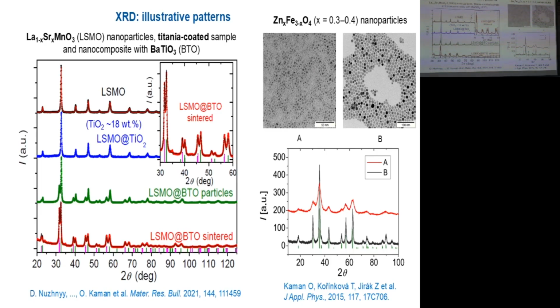We will see some typical XRD patterns. On your left side, you will see four patterns measured on some nanomaterials. This first pattern is XRD for a perovskite phase composed of lanthanum, strontium, manganese oxide. And you clearly see some diffraction lines that are very characteristic for the given structure type, for the perovskite. Basically all phases with this type of structure will have exactly this pattern in XRD, and depending on their lattice parameters and composition, the lines will be shifted, or the intensity will be somehow modified.